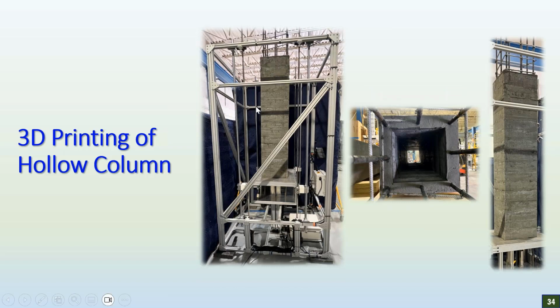This is the final 3D printed hollow column specimen, and as you can see, inside the printer, and when we remove it from the printer, this is the cross section of the column, which shows the inner core, and these are the longitudinal reinforcement and square spirals which are coming out of the shell, which were introduced inside the printing process.